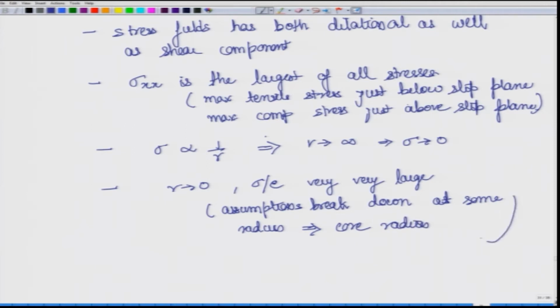So, you can look at it in terms of stress and strain fields, and later on when we talk about energy, you can look at dislocations as two parts, one where you have the elastic component and one where you have the core component. There is a core component where whatever relations we have described are not valid, and if you really want, you will have to use a non-linear elastic model, and on the outside the relations we have derived will be valid, and all our energy relations that we will move on to next will also be valid.